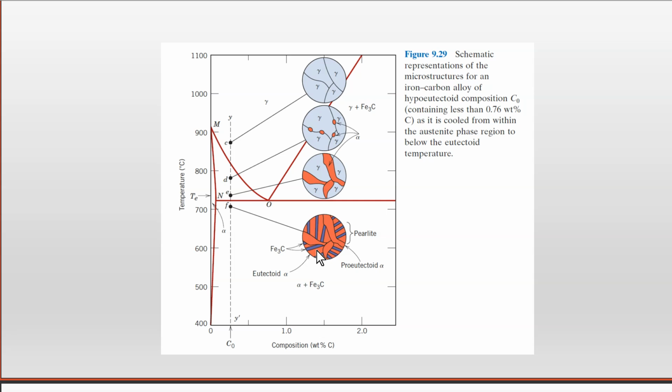So we're going to have pearlite regions which are separated by pro-eutectoid alpha. Pro-eutectoid means it's the first phase to form as we cool the austenite, the gamma phase. As ferrite is quite malleable, this gives us a material that is strong but malleable, otherwise called a mild steel.